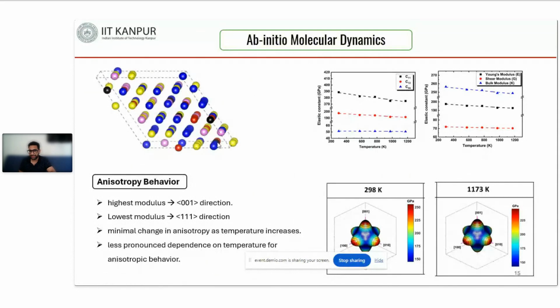Once we got a relaxed structure, we found the second order elastic constants, and from the second order elastic constants, we calculated the bulk modulus value and the bulk elastic constant. We compared the Young's modulus calculated from the ab initio MD simulation and from the experiment. The values are not exactly matching, but we got a comparable result.